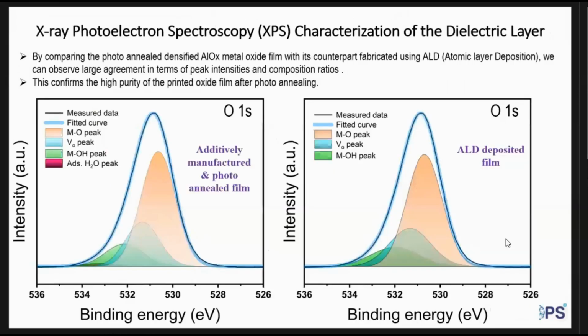Okay, so how does it differ from ALD deposited dielectric, alumina, for example? We did an XPS and compared the printed one on the left side, printed additively and photo annealed like you saw in the previous slide, with the ALD. It looks pretty comparable. The properties look very good. The cross section shows amorphous structure, void free, which is very, very important. So that made us happy with the material that we printed.